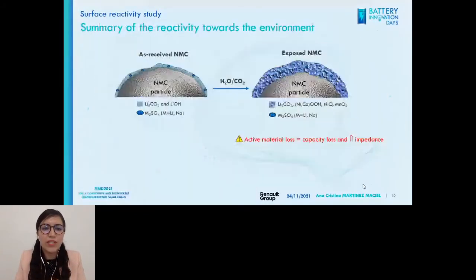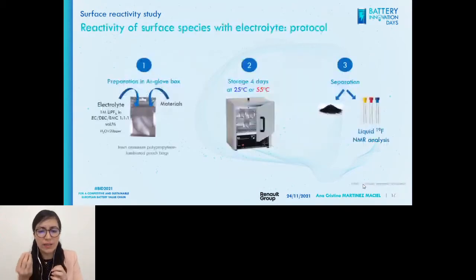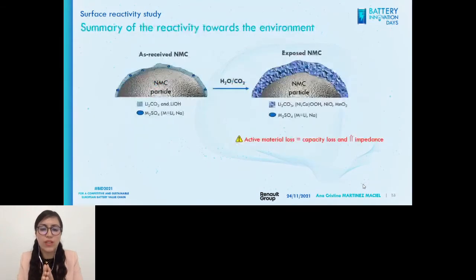So with this information, to summarize: the received materials contained a surface species on the surface. This is normal, but what is very bad is that upon air exposure, even the slightest bit of air, they will produce oxyhydroxides, oxides, and carbonates, which is bad for capacity loss and because they also increase the impedance.